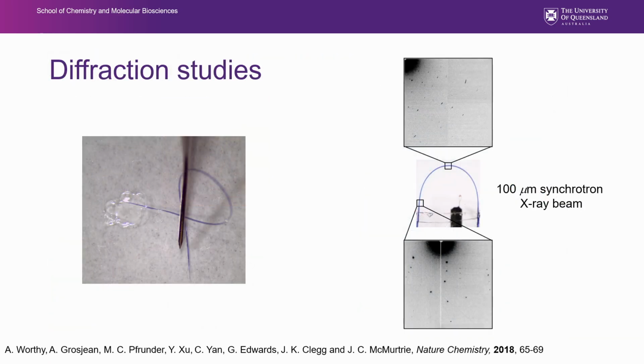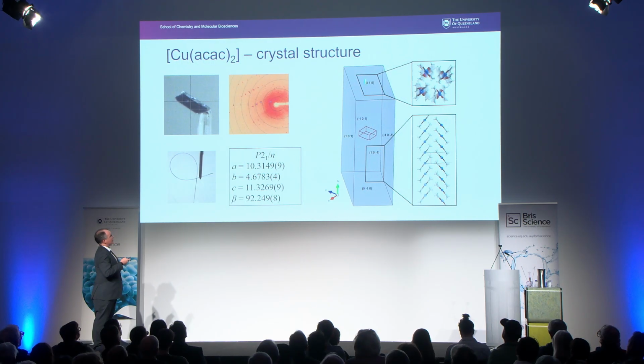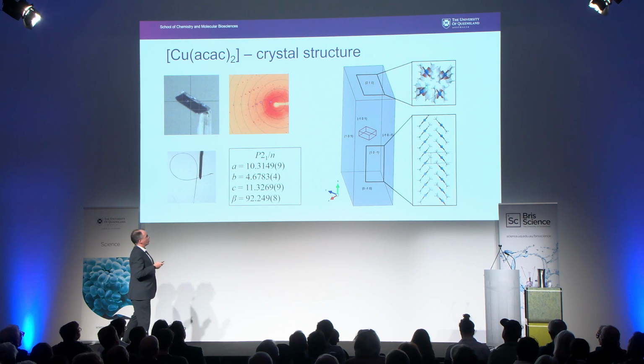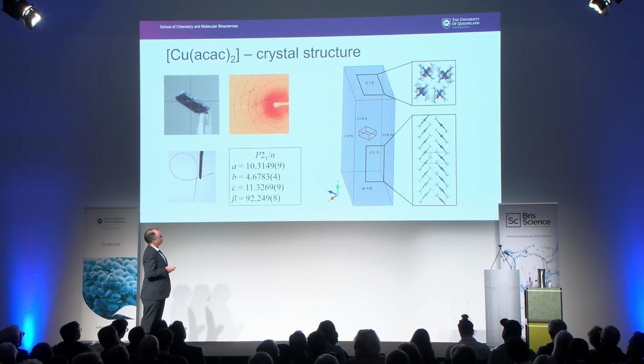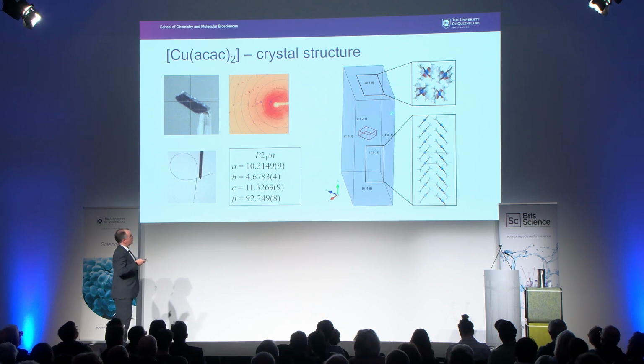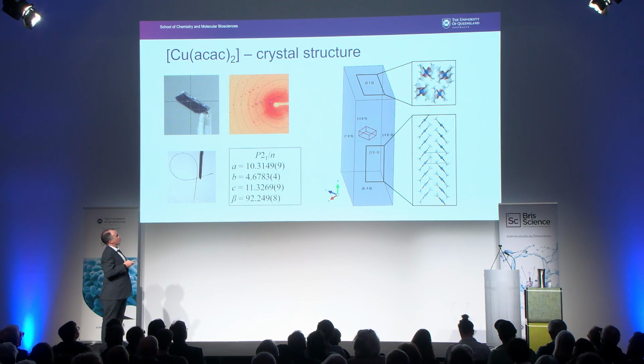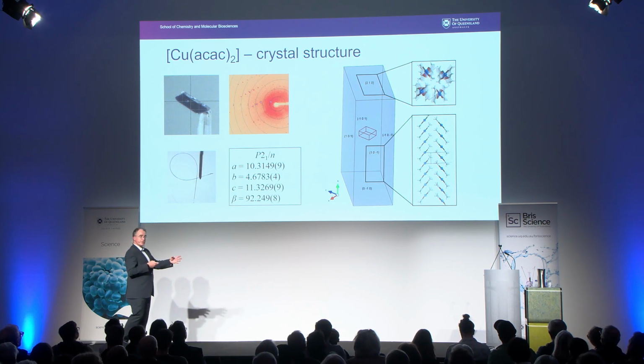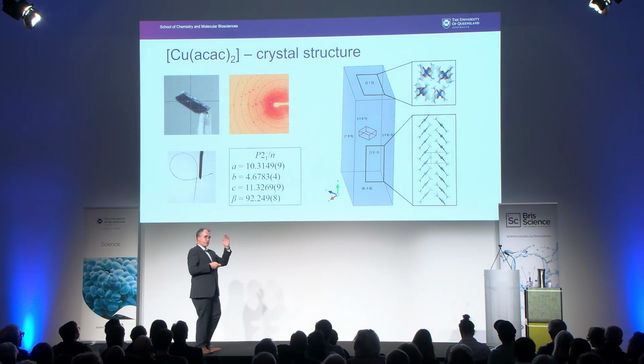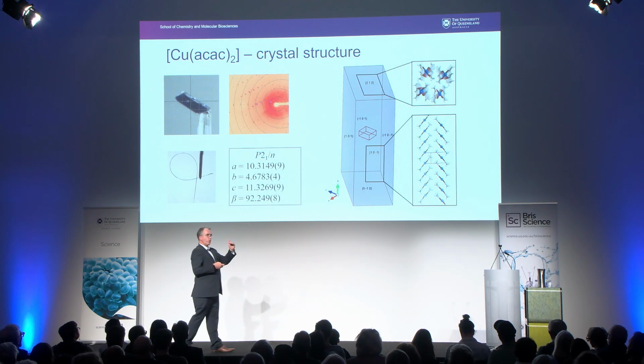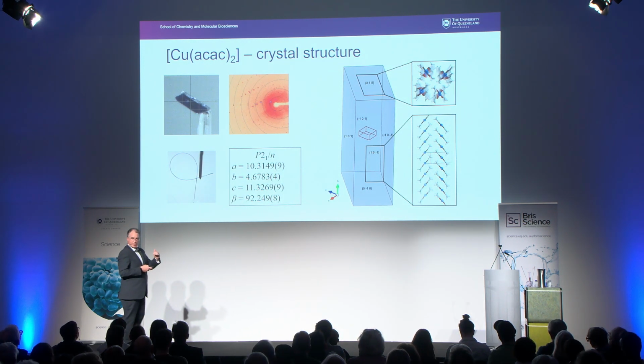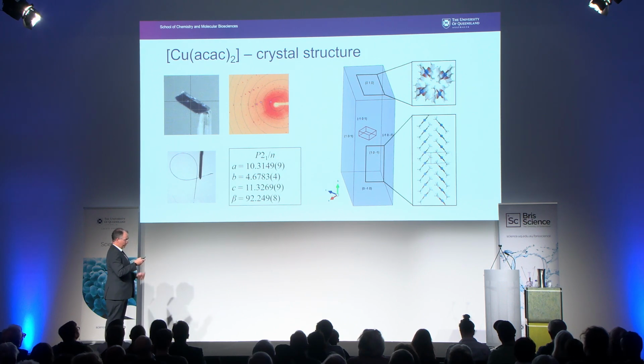So here is a picture of a crystal of copper acac with some molecules within it. When we look at the crystal structure, we again see that there's a stack of these molecules with a pi-pi interaction between them that runs all the way up the length of the crystal. But when we look down the length of the crystal, there's only very, very weak van der Waals interactions between those molecules. So this is good because it's consistent with our hypothesis. We want strong interactions in one direction, and roughly orthogonal to that, we want much weaker interactions. So we're starting to build up some more information here.